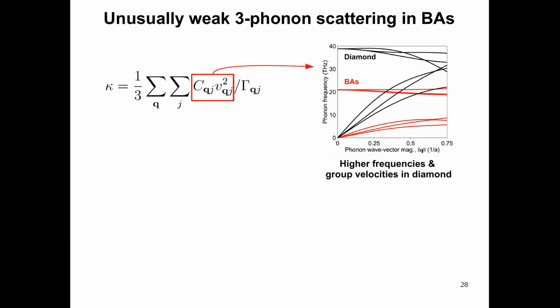Before I go into my work on boron arsenide, let us first think about why boron arsenide's thermal conductivity is higher than diamond, even though the conventional guidelines predict the opposite trend. To do that, let's go back and look at the thermal conductivity expression. If you look at the phonon dispersion comparisons between diamond and boron arsenide, because diamond is lighter, it has stiffer phonon frequencies, in which case the group velocity, which is the slope of these curves, is higher for diamond compared to boron arsenide. So clearly in the numerator for thermal conductivity, diamond wins over boron arsenide to get a higher weightage.